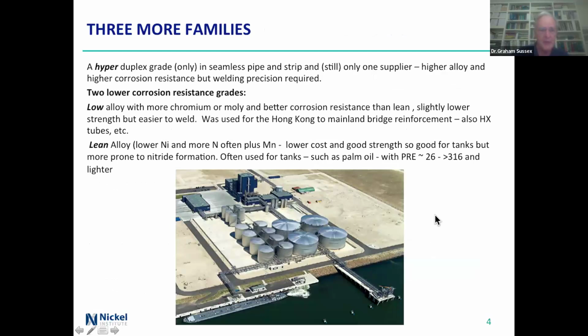There are 3 more families. The hyper-duplex grade, I don't have a picture of them because there's basically only one supplier at the moment. Seamless pipe and strip, and welding them can be quite difficult. The 2 lower grades, the low alloy ones, a bit more chrome and moly, better corrosion resistance than the leans. Not a lot of difference. You'll see that in a minute or two. Slightly lower strength, but pretty much easier to weld. Was used, incidentally, in the Hong Kong to mainland bridge reinforcement, but more commonly heat exchanger tubes, that sort of thing. The lean alloys, lower nickel, often more nitrogen, because otherwise it doesn't stay properly a duplex. And for getting the nitrogen in, often has higher levels of manganese than you normally expect. Lower cost, good strength, great for tanks.